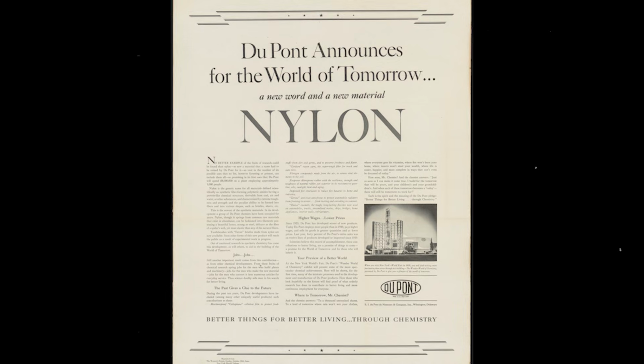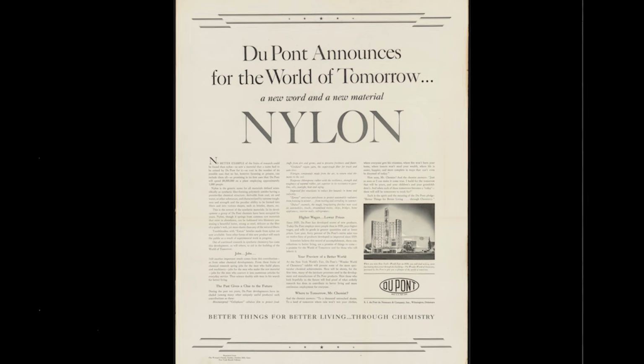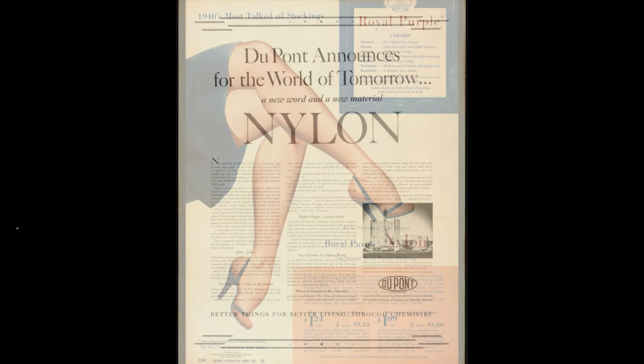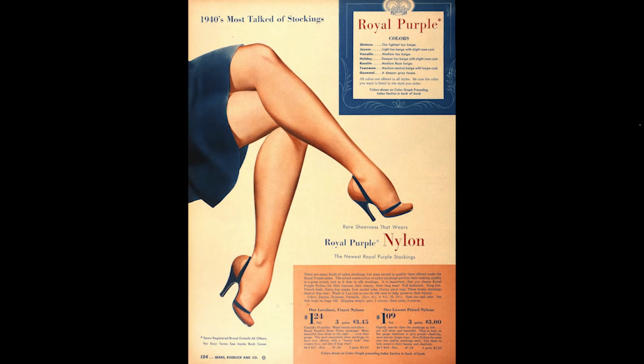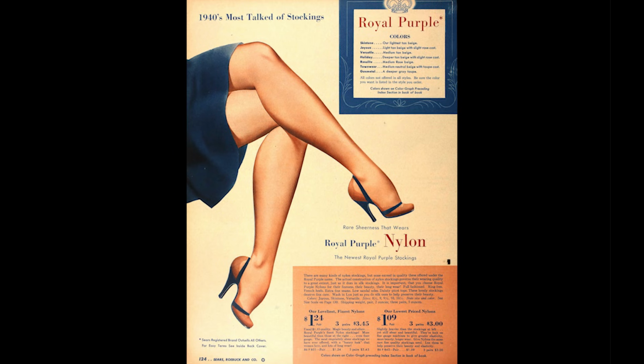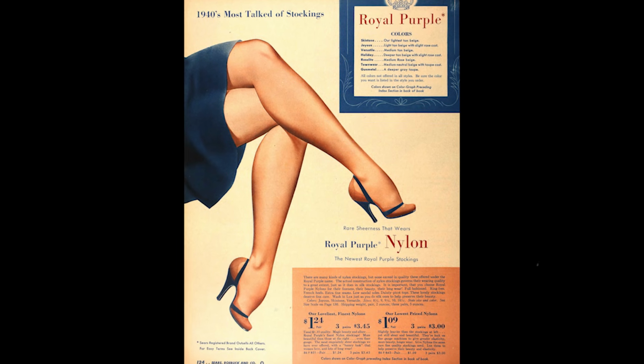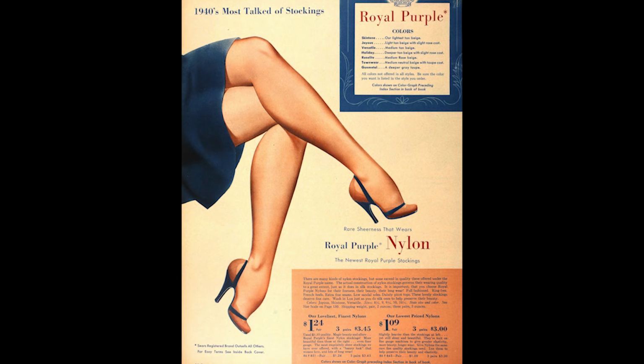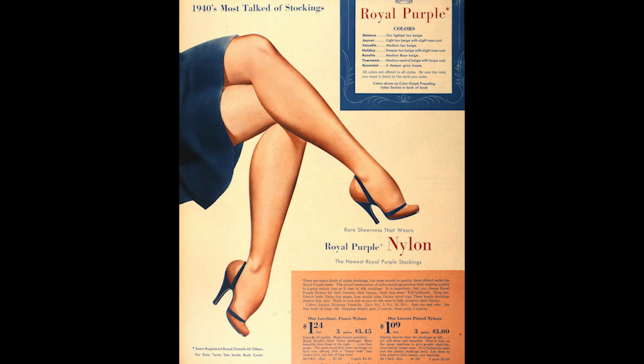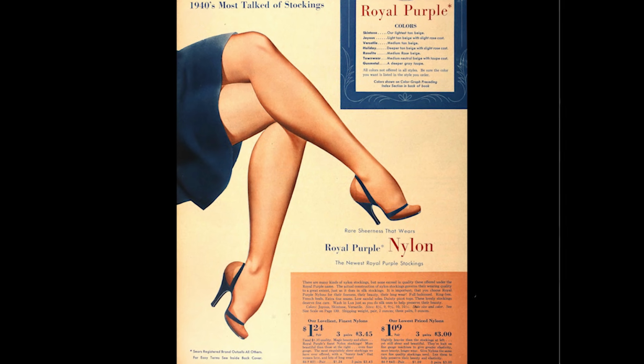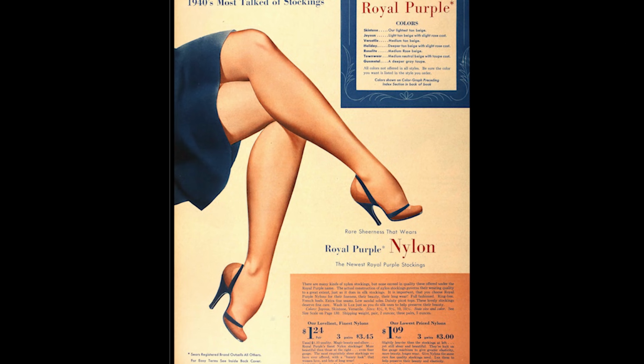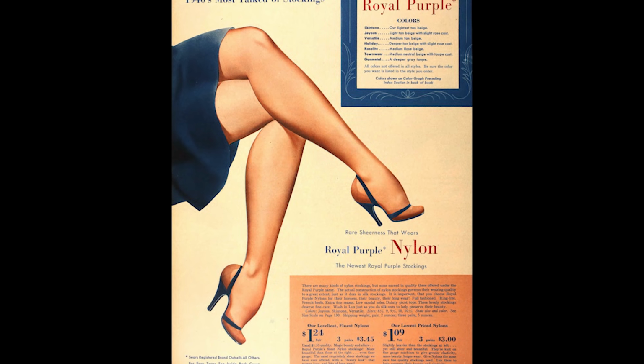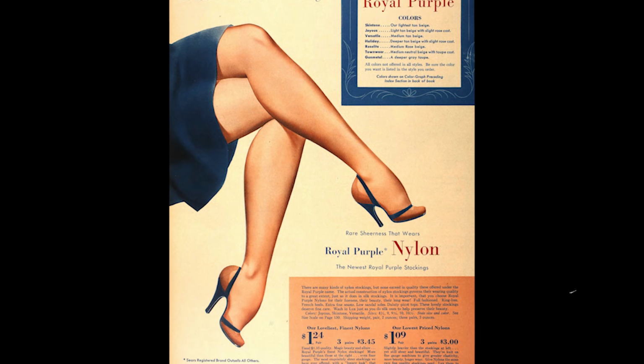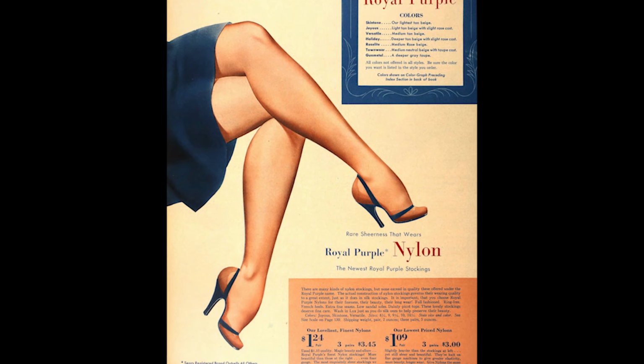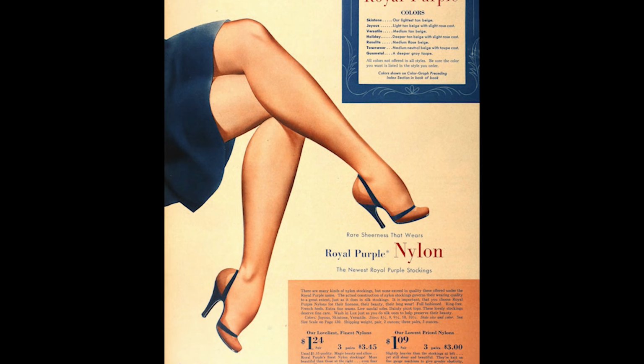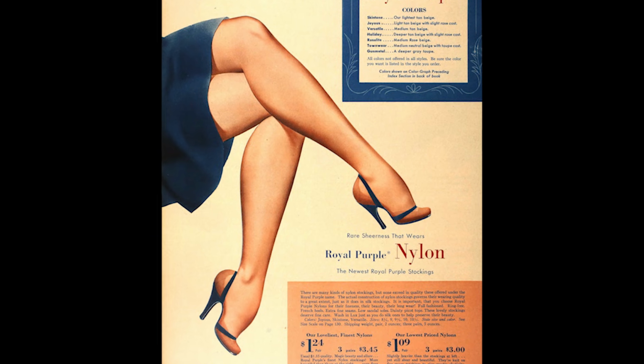The most significant breakthrough came through understanding that nylon's molecular structure could be modified after the fiber was produced. Heat-setting techniques allowed manufacturers to stretch newly knitted stockings over precisely shaped forms, then apply controlled heat and humidity to lock the polymer chains in their final configuration. This process created stockings that fit perfectly and maintained their shape even after dozens of washing and wearing cycles. The molecular bonds that were temporarily loosened by heat treatment were formed in the exact positions determined by the shaping forms, creating permanent dimensional stability that natural fibers couldn't achieve.